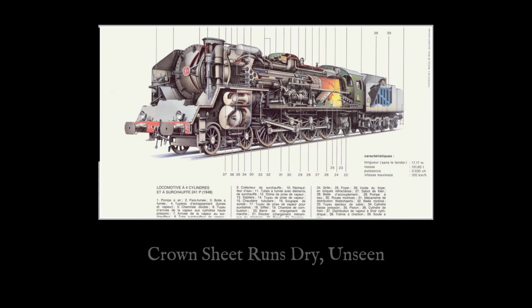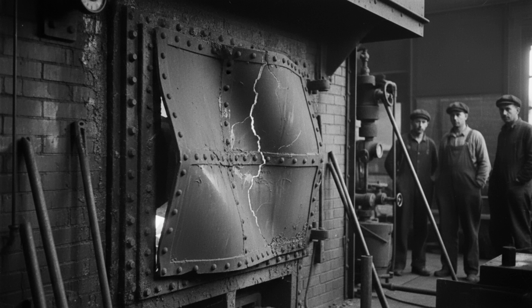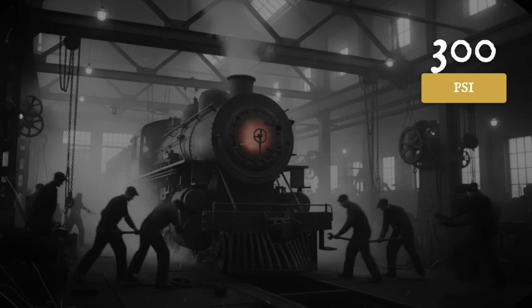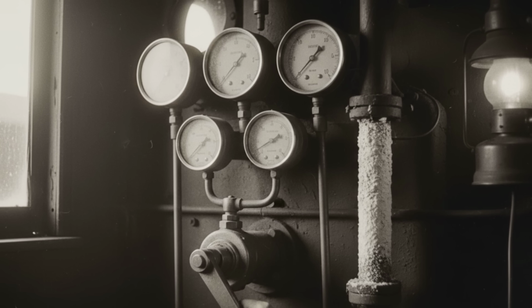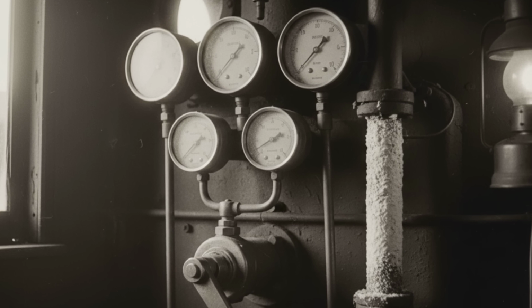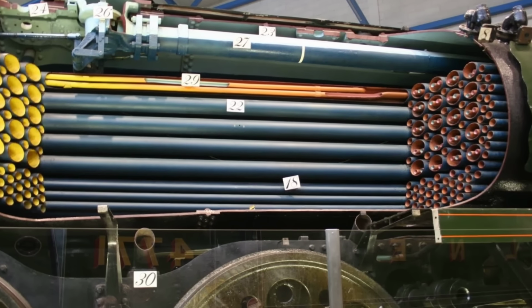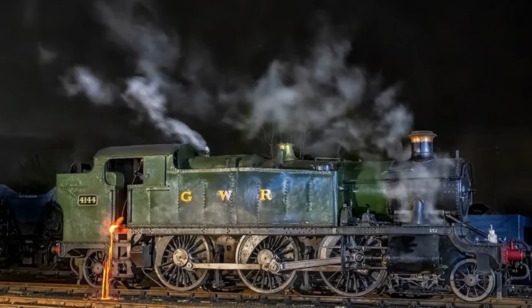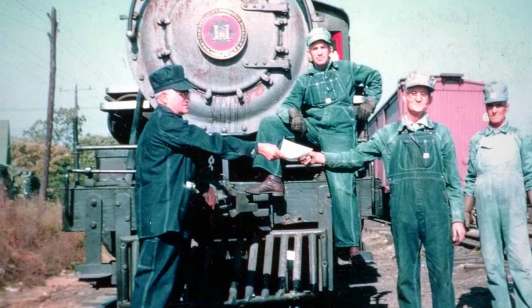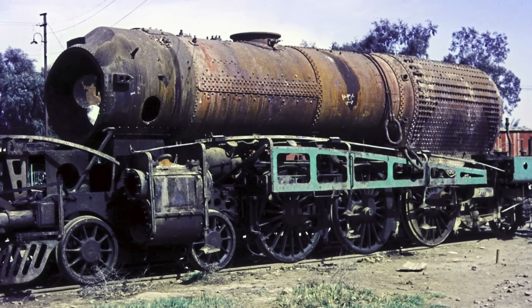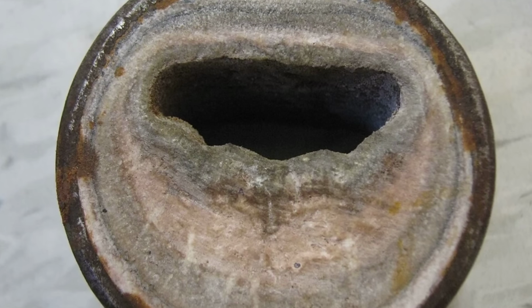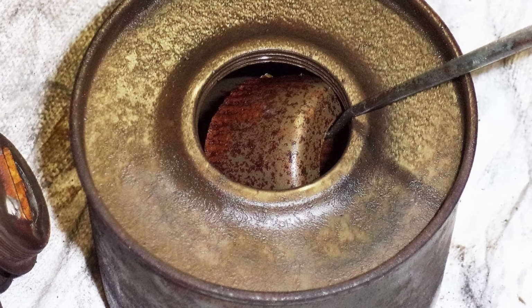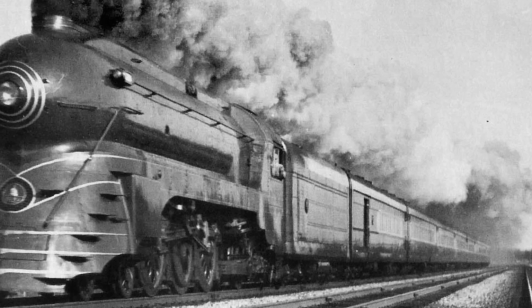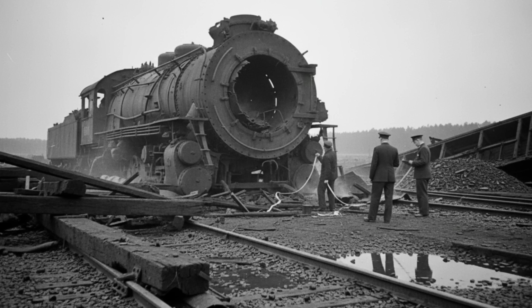Inside, the waterline drops below the crown. Steel that once shrugged off 55,000 PSI now loses its will at 1,200 degrees. The margin is gone. No alarm sounds. The only warning is a rising tick in the firebox, a subtle shift in the color of the flame. By the time the crew notices, the weakest link has already failed. A scale plug, a failed injector, a forgotten filter, each one a microscopic betrayal. In the world of high-pressure steam, the smallest oversight writes the largest headline.